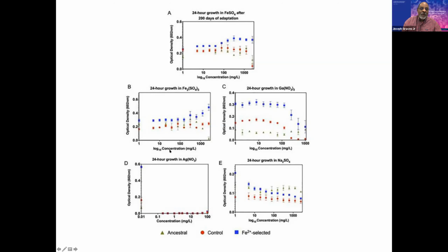Now, what we found shocking, and I must say I was floored when I first saw these results, is that iron 2 resistance confers no resistance to silver. The reason you can't see anything in this graph is because ionic silver kills the iron 2 bacteria, it kills the controls, it kills the ancestors, okay, at all concentrations tested.